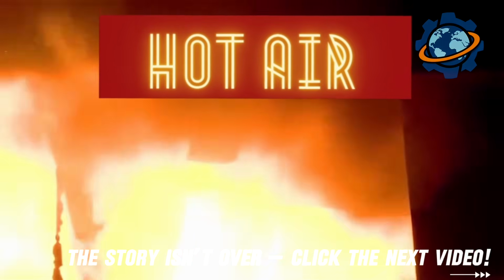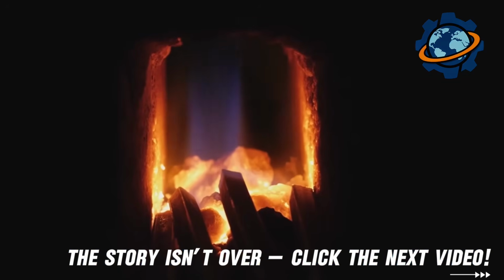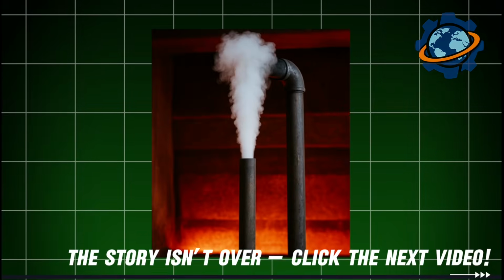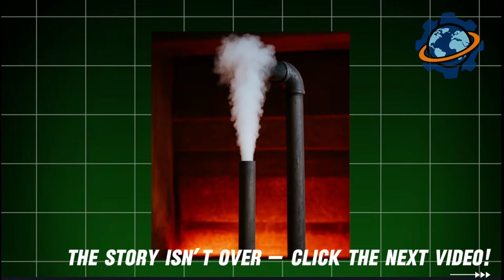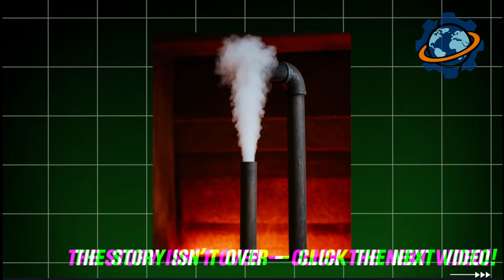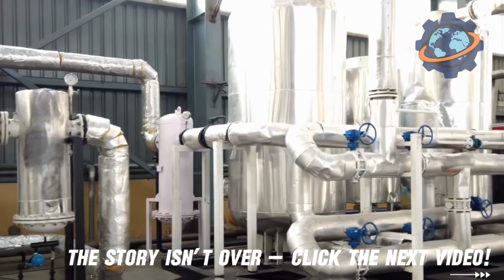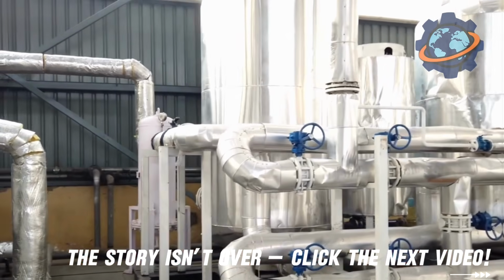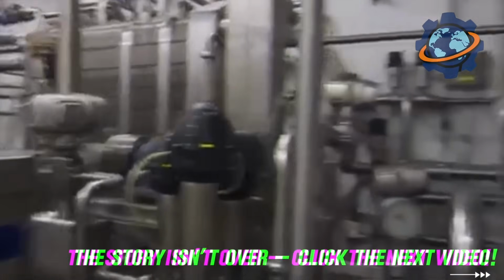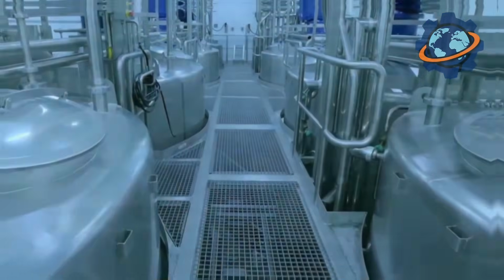Zinc doesn't melt. Its boiling point is only 1,665 degrees, but the furnace is at 2,200. So zinc immediately turns into vapor, metallic vapor. Inside the furnace, atoms of gaseous zinc are flying around. The vapors rise up and exit the furnace through piping. They enter a condenser, a special cooled chamber.